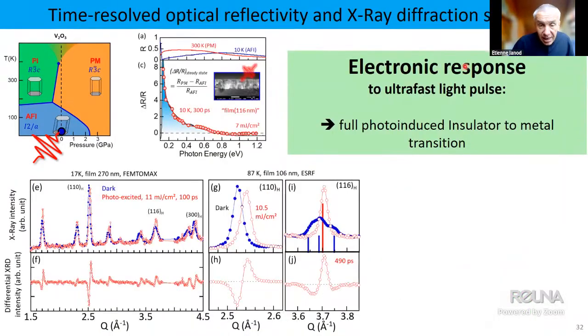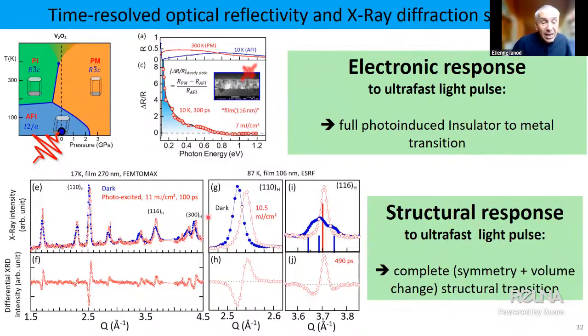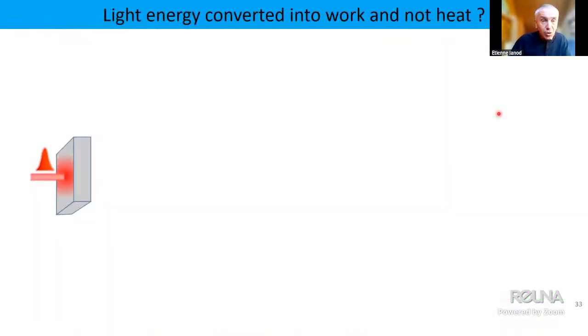And in fact, this is the electronic response, but we have confirmed this electronic response by the structural one. The structural response confirms exactly this scenario. Here you see the XRD pattern at rest in blue and after photoexcitation, in this case after 100 picoseconds, and you see a spectacular evolution. You have a shift toward higher Q, which means a compression. And also you see that the 3 monoclinic Bragg peaks merge into a single one, as expected if we have a transition from the monoclinic to the hexagonal phase. I don't go into detail, but trust me, the transition is complete, both from the structural point of view and from the electronic point of view.